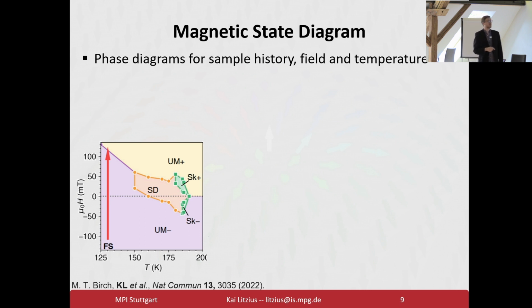So let's talk about first what happens when we just sweep the field. This is just a simple field sweep. We go from negative field to positive field and check what the sample looks like. So in the lower part here, we've got uniform magnetization in negative direction, and then we go into uniform magnetization in positive direction. So it just flips along the easy axis and is done. Now if you warm it up, you see a typical behavior of crystalline materials, where it goes through a stripe phase into a uniform phase, and near TC we've got skyrmion pockets. This is kind of similar to what you expect in a B20 compound, for example.